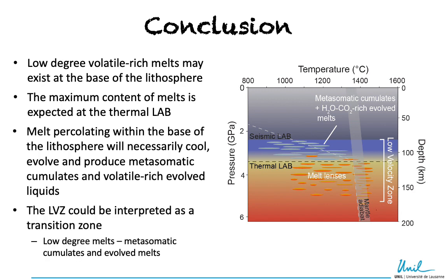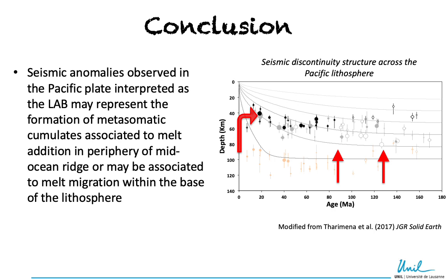All this information suggests that the low-velocity zone may correspond to a transition zone with low-degree melt at the top of the asthenosphere, evolving to the metasomatic cumulate, including various proportions of volatile-rich differentiated melt in the base of the lithosphere, as illustrated in this figure. Considering the seismic anomaly observed in the Pacific plate, we suggest that this anomaly, interpreted as a LAB, may represent the formation of metasomatic cumulate associated with the melt addition in the periphery of mid-ocean ridge, or may be associated with melt migration within the base of the lithosphere.